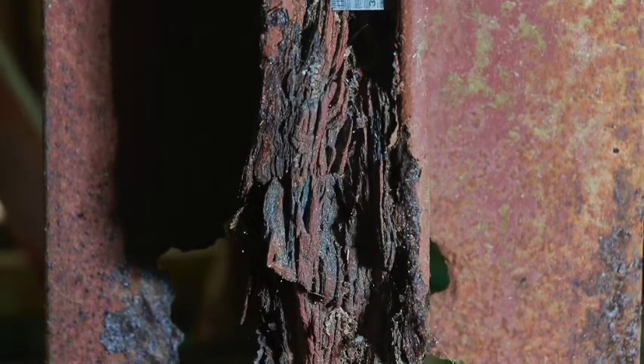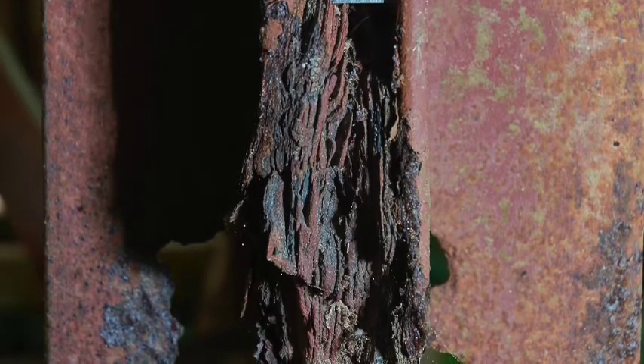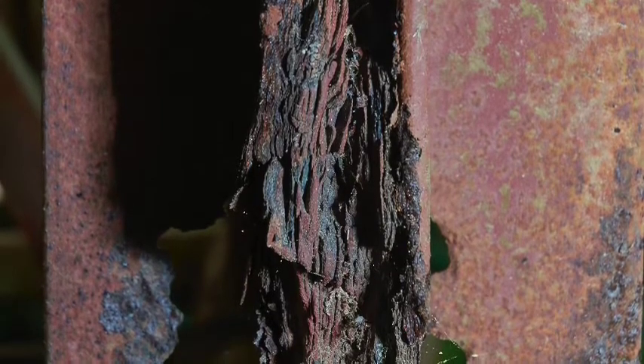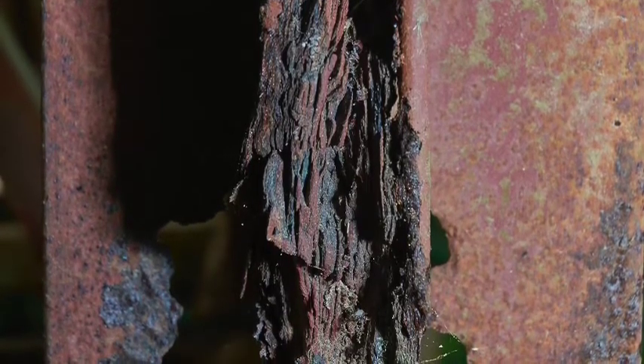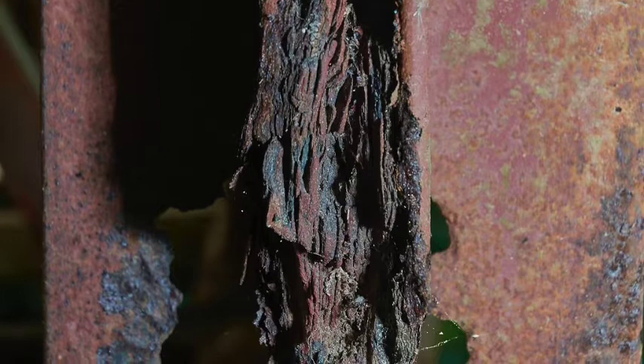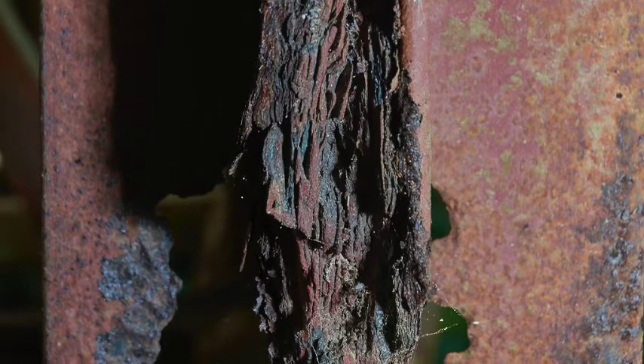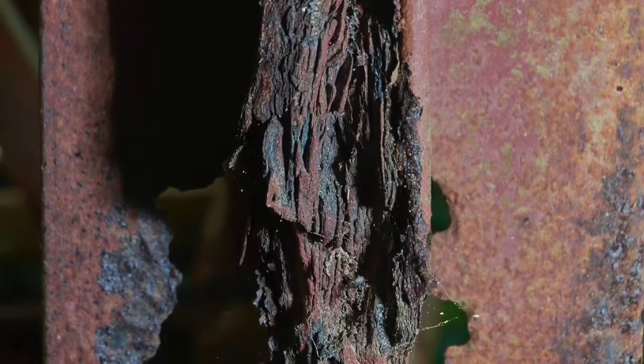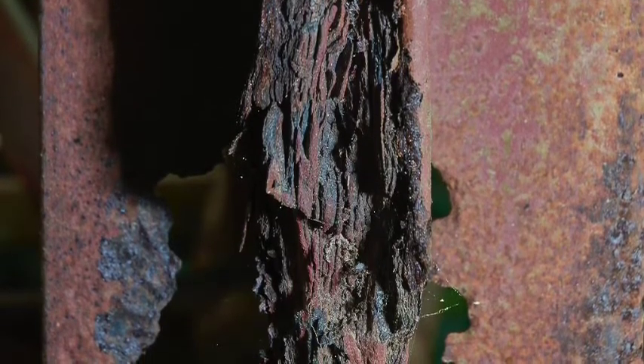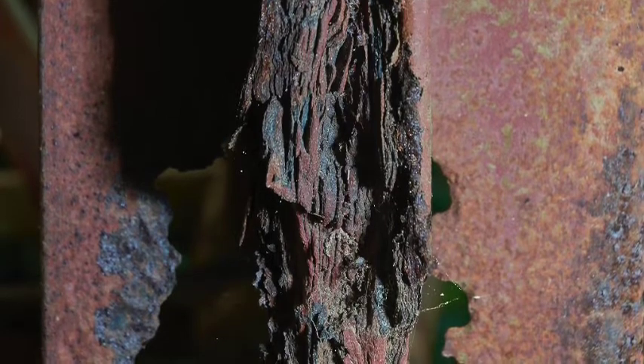Right. So basically in this situation whereby you've essentially got two vertical pieces of steel that are about 15 or 20 millimeters apart from each other, not only do you have the corrosion weakening the inside, but the steel that's still intact on the outside is actually being pushed outwards by the corrosion. So it's almost as if you've got a car jack between these two members and started jacking them apart. That's what's happening, on top of the corrosion. Yeah. Crevice corrosion can be seen in these sorts of circumstances right down to where corrosion's begun to occur between mating surfaces. You were saying that there was about a 15 mil gap there.